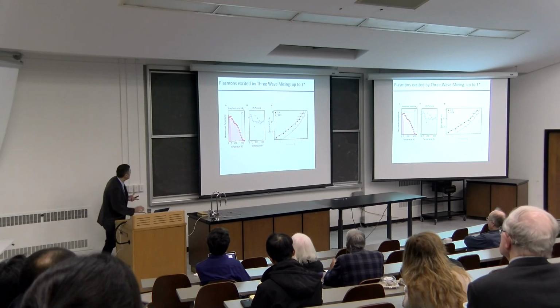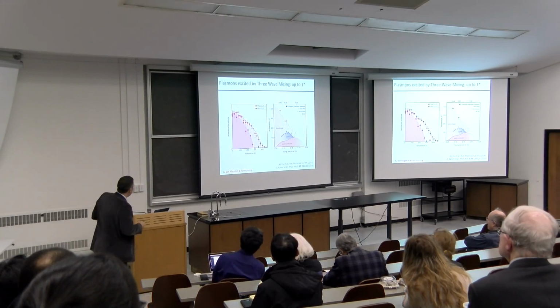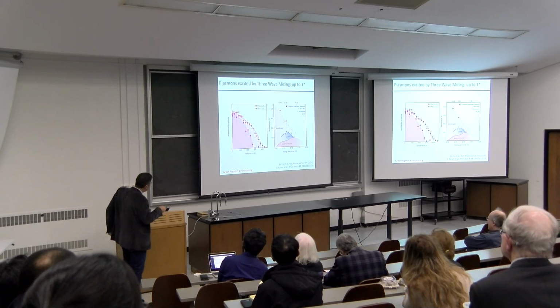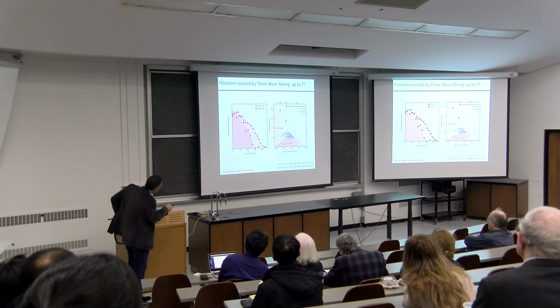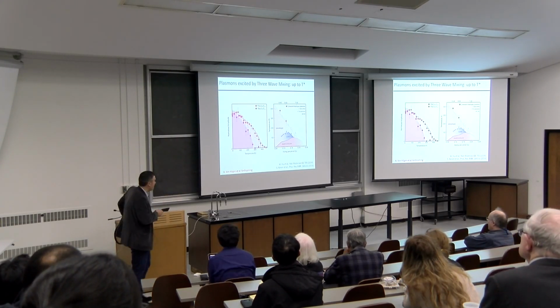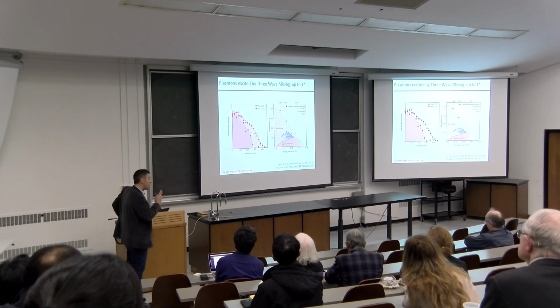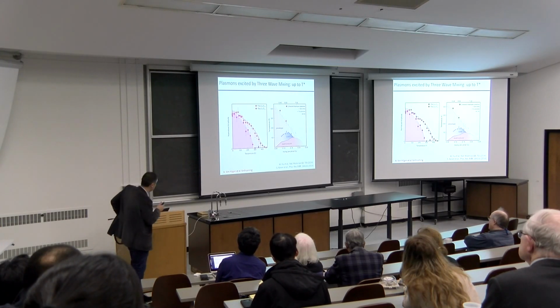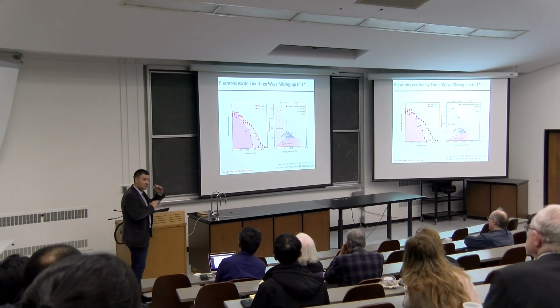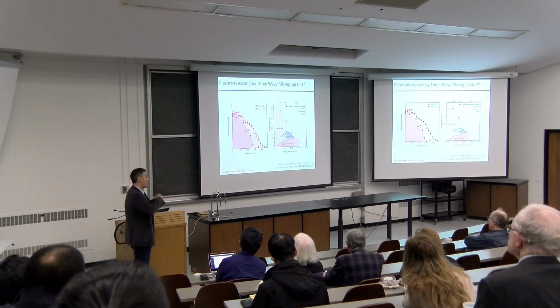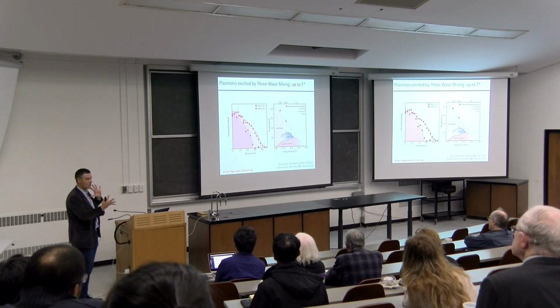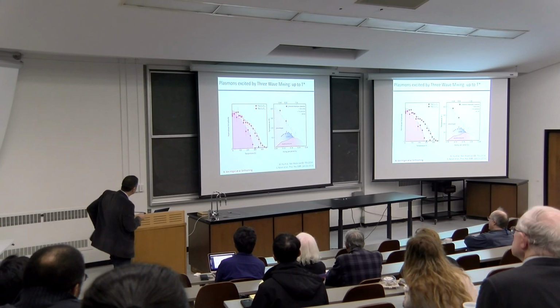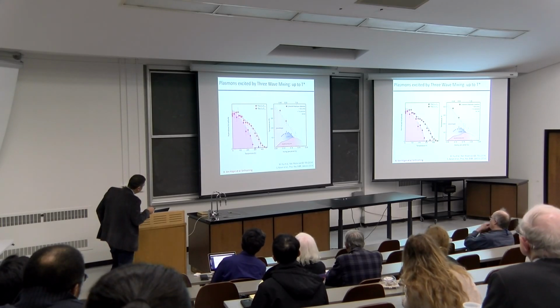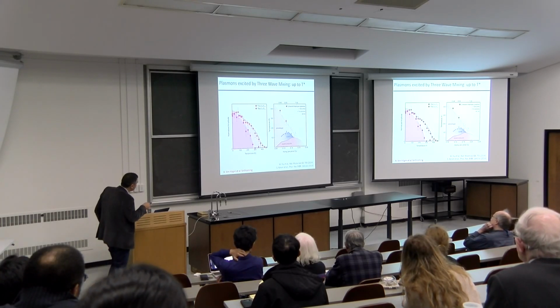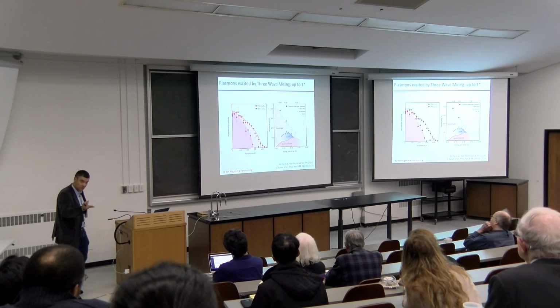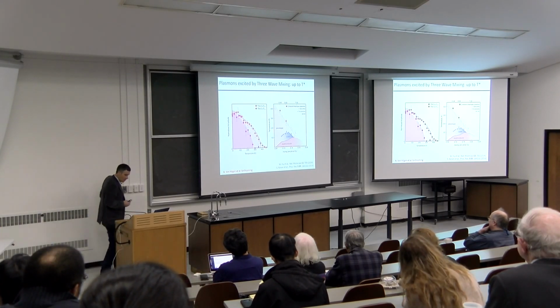So what I did is that I can measure in a different compound, redo the whole experiments, meaning Alex can do this. Another sort of 8 months of his life. And what you can see is that if you take a different compound, it doesn't go away at 380 Kelvin, but at higher dopings, it goes away at 270 Kelvin, okay, in YBCO 6.65. Unfortunately, if you go to higher dopings, in case you were going to ask this, the frequency matching between the phonon and the two plasmons goes away. So this is not a comprehensively applicable method. It's just something where we are getting lucky in this specific compound and we're able to see this, okay? But this matches very well. This is stuff that I stole from various publications, and I can generate these parametrically amplified oscillations, which I'm attributing to the Josephson plasmon, all the way to room temperature.